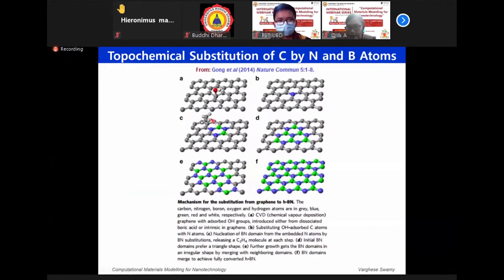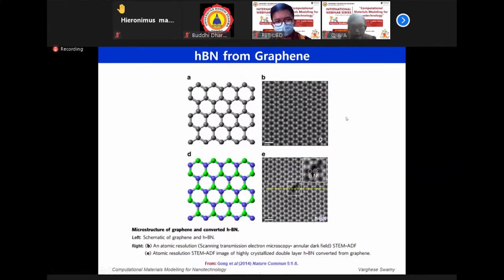Now, starting with graphene, through topochemical replacement of carbon atoms with boron and nitrogen in a CVD process, you can create different hybrid structures. So when we go from graphene, which is a semi-metal, all the way to hexagonal boron nitride, which is an insulator, we are going through different types of semiconducting states depending on the hybrid structures that we create. So we can essentially tune the band gap when going from graphene to HBN through producing various hybrid structures. And this can be done using a certain type of CVD process, which has been published by Gong et al. in Nature Communications in 2014. So this one shows the experimental electron microscopic evidence for starting with graphene, the full conversion to boron nitride.